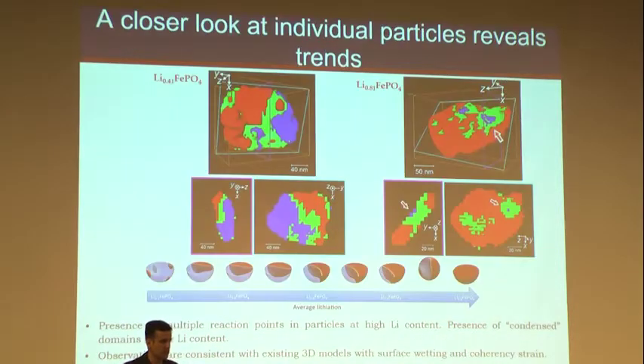But then we could start extracting individual particles and doing virtual sectioning and looking at the chemical domains inside. These were a little thin to make a lot of argument about resolution inside the particle in depth. But there were a couple of them that were thick enough that we're confident that what we're seeing is within the particle. The states here are the result of integrating the overall chemical state of the sample and, based on the ratio of iron 2 and iron 3, extracting an amount of lithium that it contains.